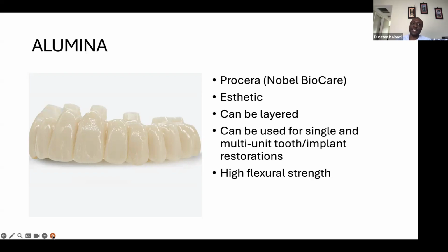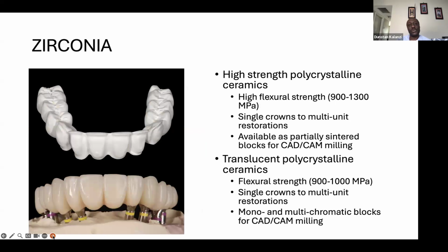This is for historical purposes, so the chances are high that many of you will never have work that has an alumina core, because right now most of the work is based on zirconia. So let us talk about zirconia, which is of course the in thing for most of our work. And this can be divided into high strength polycrystalline ceramics. And all this is based on the amount of a component called yttrium. Based on how much is within the ceramic, that determines whether it is high strength or translucent polycrystalline ceramic.